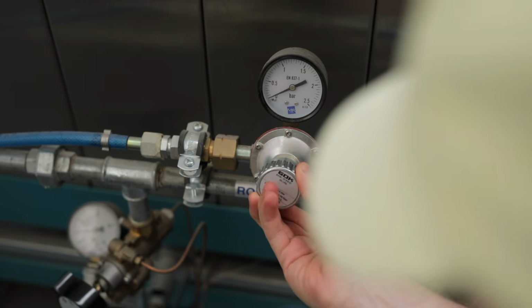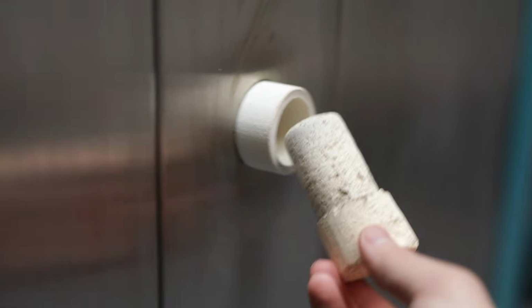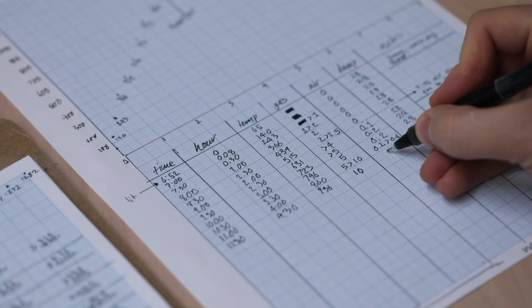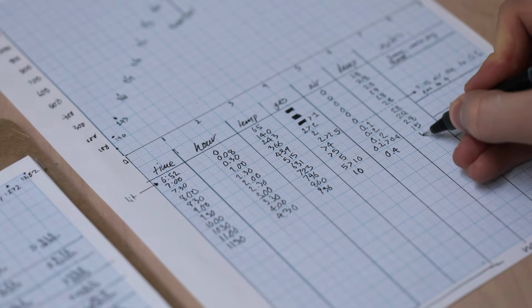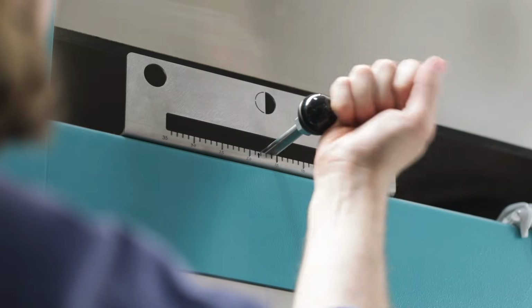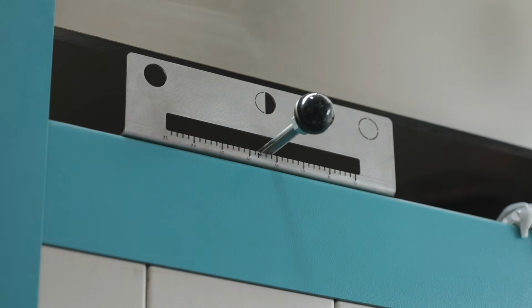I do this by sliding the dampers halfway over the exit of the flue, and by increasing the gas pressure and air pressure quite dramatically. The partly covered flue throttles how quickly the exhaust can escape, and quite quickly the gas inside will start to burn inefficiently. And as the flames seek more oxygen to burn with, fire will start to jettison out of the spy holes and flues at the back. As there isn't enough oxygen inside the kiln, to find it, oxygen molecules are pulled out of the clay and the glazes of the pots. And this is ultimately what provides the green tones you'll see at the end.